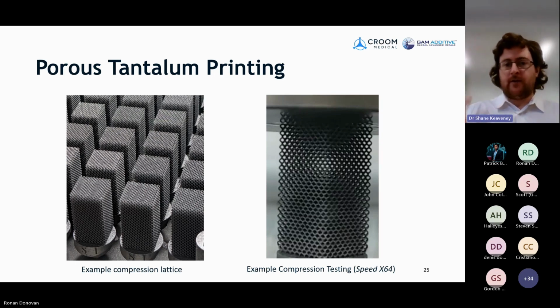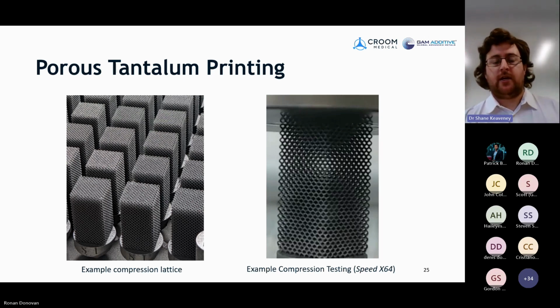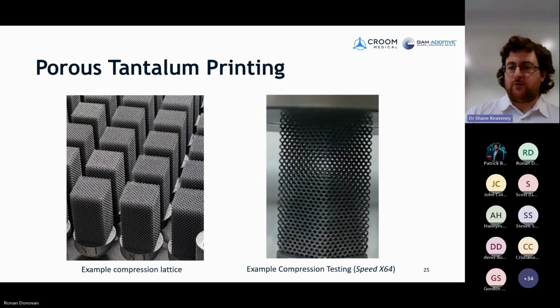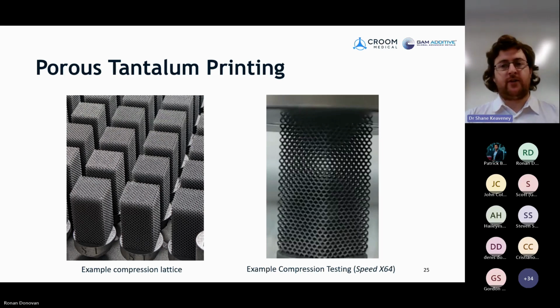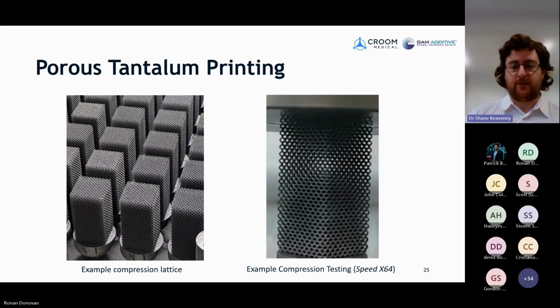If we compare that with other materials, we mightn't see the same results. Due to the high ductility and this toughness that I talked about with tantalum, this is why we're seeing such a large reduction of our compression sample without a real failure. And again, through our DOEs, we've seen quite a range of compressive strengths that we can achieve here, linked to both the power input or the energy input that we're doing, but also linked to the overall strut size of the beams here on the compression samples. So that covers in terms of solid and porous. We've done quite a good work. We have quite a deep understanding of the capabilities and the behavior of the material.